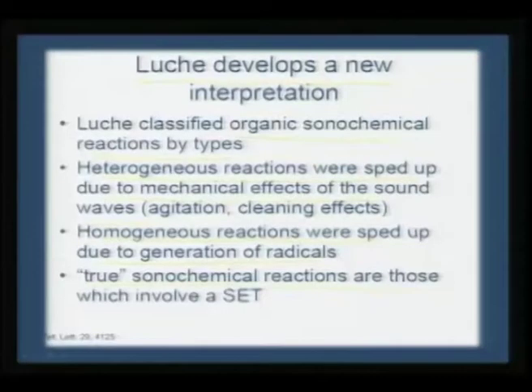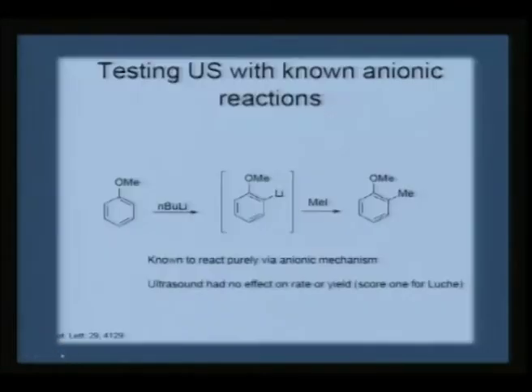True sonochemical reactions are those which involve SET, that is single electron transfer type of activities. So we can see one or two examples of that. Testing ultrasound with the known anionic reactions. One such reaction is this, known to react purely via anionic mechanism. Ultrasound has no effect on the rate or yield.